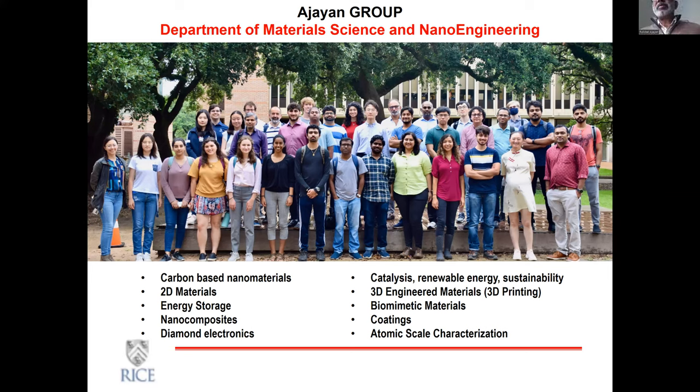I think for many of these materials that we use, atomic layer deposition has not been successful, especially to get highly crystalline, defect-free material. Of course, with oxides, maybe most of the ALD gives you disordered systems, right? I'm not very sure about oxides. But again, if you can modify a couple of those techniques to work at the scale that we are working on, even 3D printing, as I said, if you can get feature sizes in the nanoscale, then a lot of new things can be done. But ALD, I think people have tried. They do get material deposition, but they get more nanocrystalline, disordered kinds of architectures.